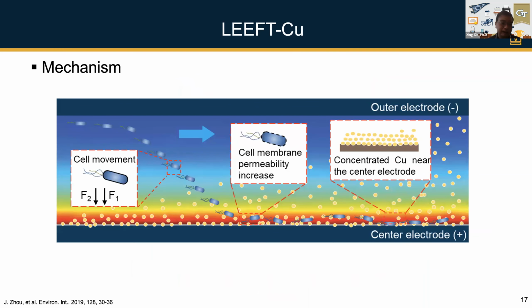Okay, and a little bit more on the mechanisms of the specific system we used for the LEEFT: we have the center electrode, right? We put the center electrode as a positive electrode. So when we apply an electric field and also a certain electric current, you can actually release copper, right? Copper is released from the center electrode. It's a copper-based electrode, so copper ions are released from the center, and you basically get a higher concentration close to the center, right? So it's a similar distribution effect. When it's close to the center electrode, copper concentration is higher.